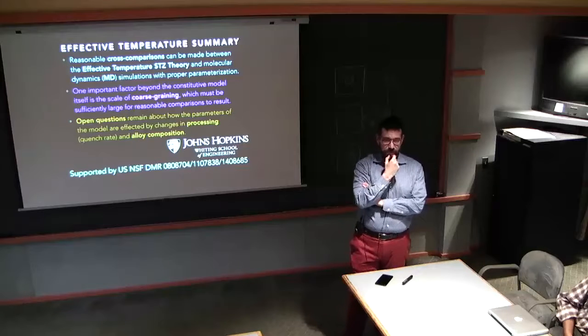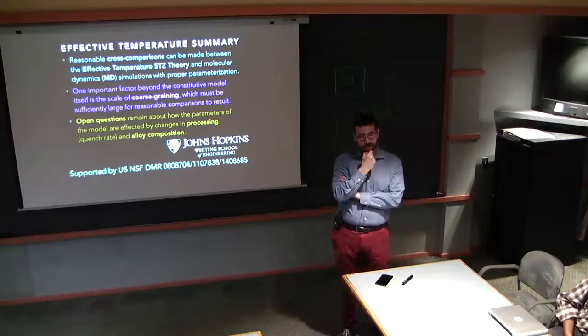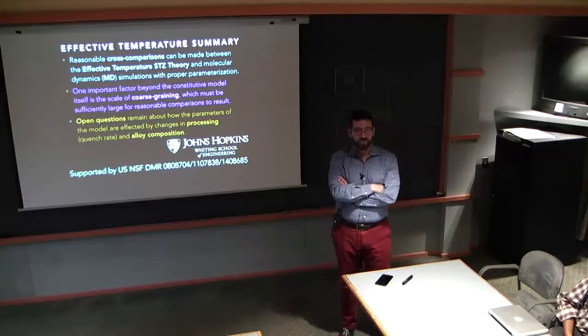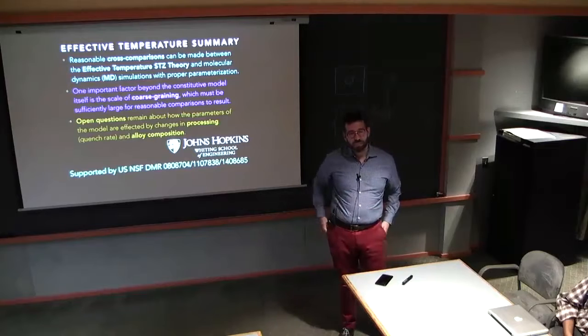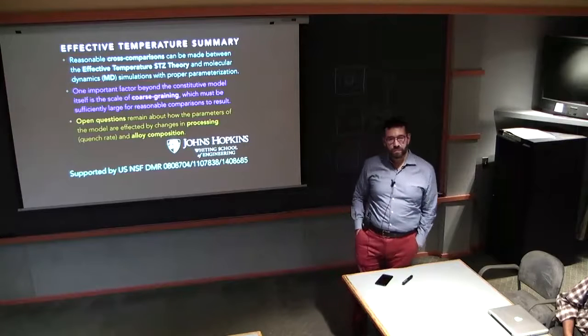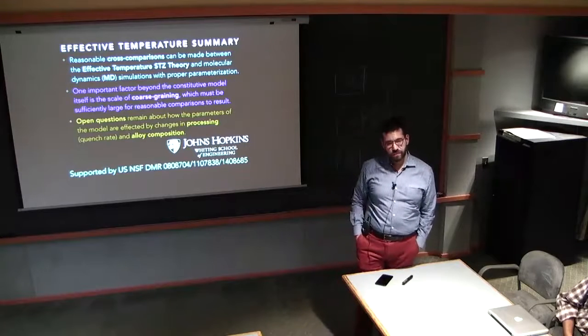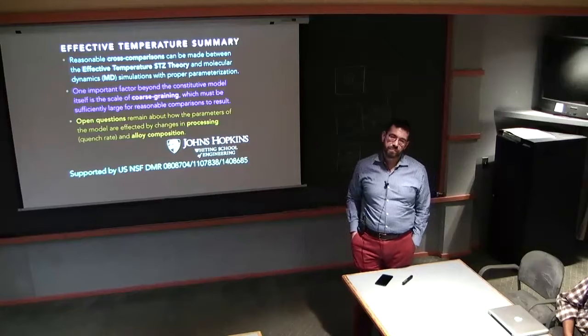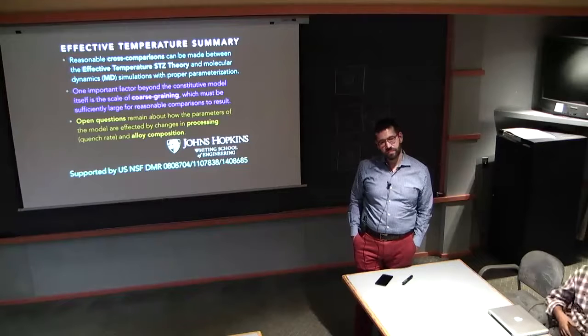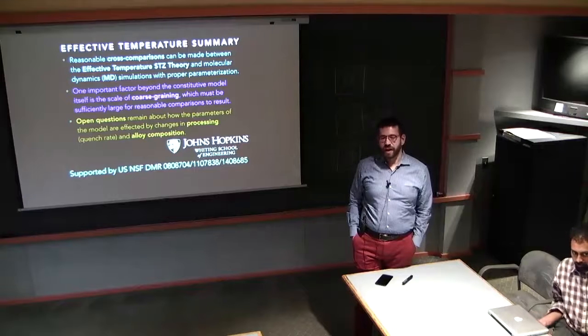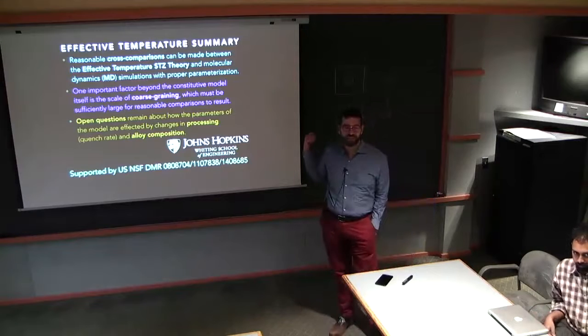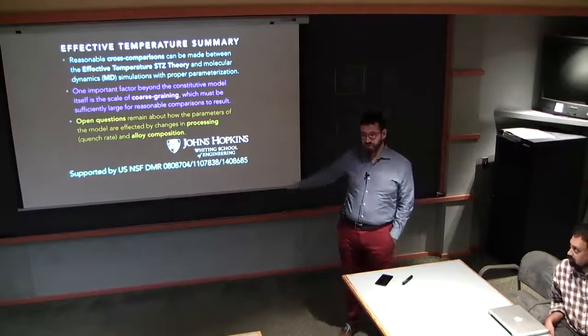My eyebrows go up when I see this, because there must be a regime in which this banding mechanism isn't the right one, where what's going on is that I have interactions between elastically triggered events. That's right. Yeah, and I think you can get that even in the athermal quasi-static.